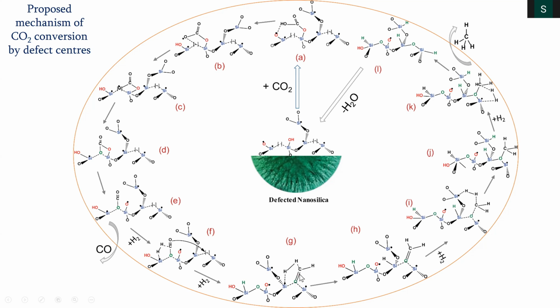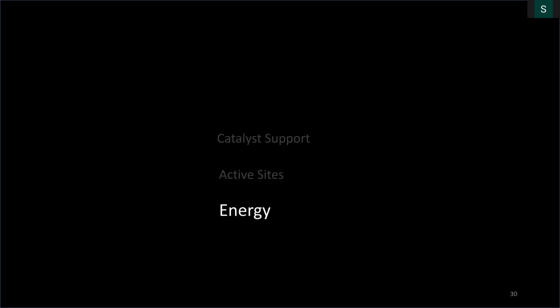type of intermediate molecule. And you keep adding another hydrogen molecule, and once you add these 4 hydrogen molecules, you get methane, and this SiH containing material, which you heat, and you again create these Si radicals and O radicals, or oxygen radicals. Right. So I will not go into the details, but this is how we propose the mechanism, which indicates that you need a proximity of the two defect centers. Okay, so that was the second part where I showed you the active site can be something other than metals.